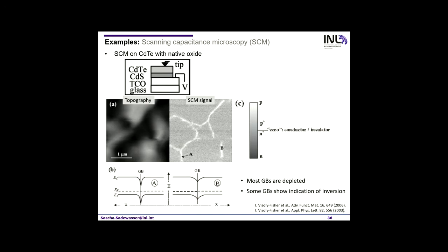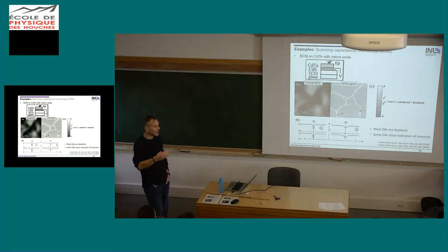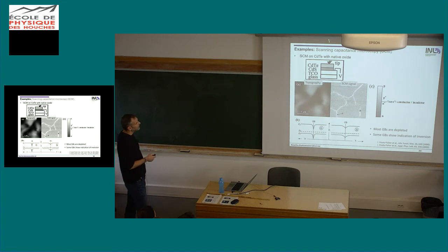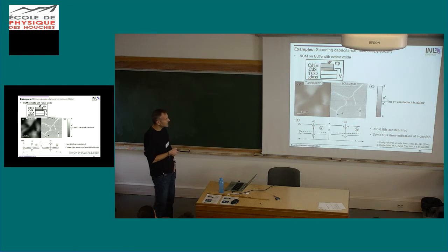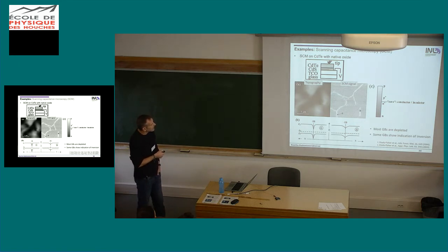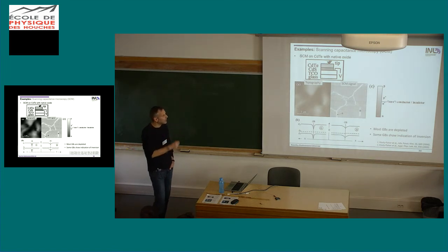And most of the examples I will show are about the grain boundaries, so there's kind of a continuous story. So here it's an example for cadmium telluride. I have on the next slide also CIGS. So what the people did here, it's the superstrate structure. We also saw this yesterday. So we have glass, TCO, cadmium sulfide, and cadmium telluride. Light would come in from here. So here we measure with the tip on the cadmium telluride, which has a native oxide. So the oxide layer here is just by keeping it in air and having it natively oxidized.